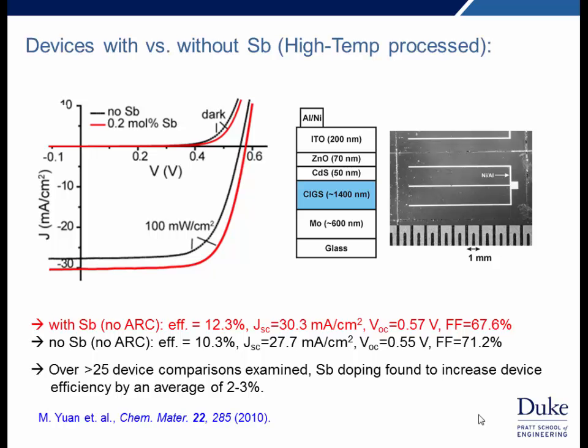And even when processing at high temperature, we still see a significant improvement in device performance, on average 2 to 3% absolute, when we introduce antimony during the deposition process. And this improvement predominantly comes from the short circuit current in the device, presumably because of better grain structure in the film.